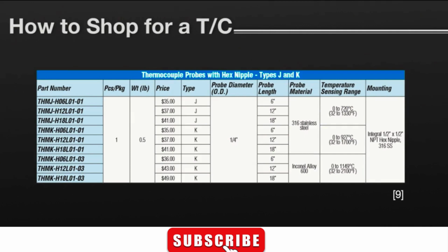The Type K probe will work reliably up to the upper range of its calibration, in this case 1149 degrees C, but only if you specify the Inconel material for the probe sheath. The 316 stainless steel probe sheath would corrode at this temperature and ruin the thermocouple inside.